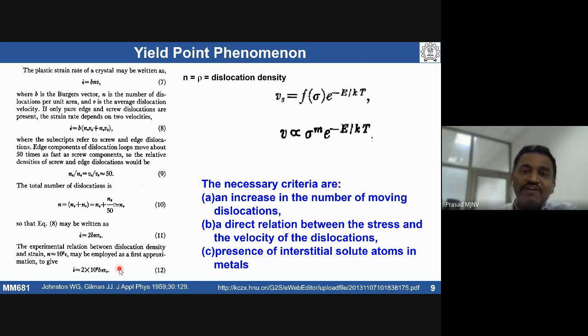But it will not fail. Since the material is not failing, what does it mean? Actually your dislocation density is locally already increased, so that can lead to a reduced velocity. That means we are going to see a lot of multiplication - all those things can bring down the velocity of dislocation. So that decrease in velocity is going to give you that drop in stress in the material.